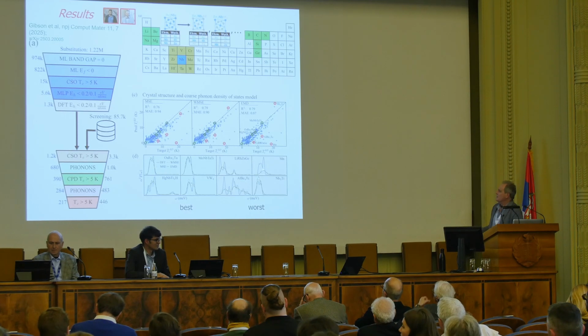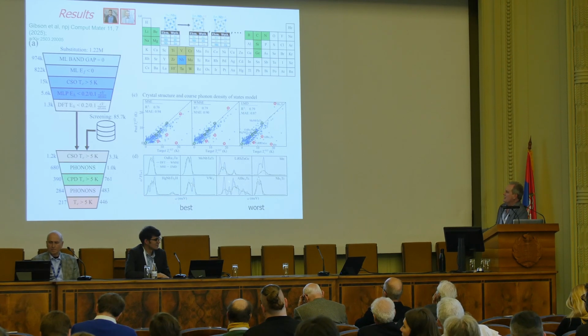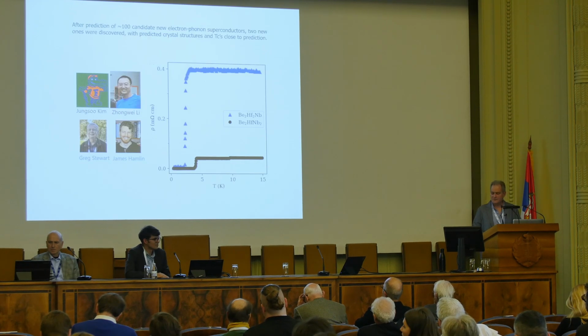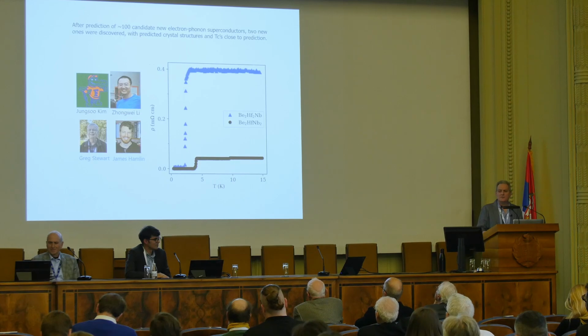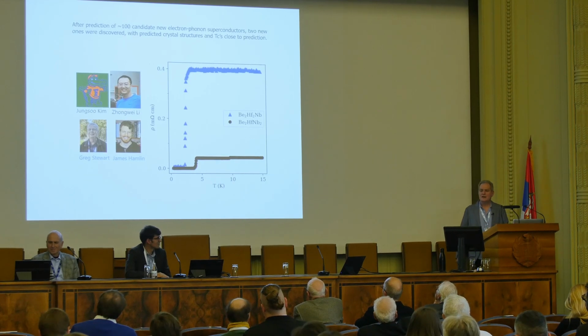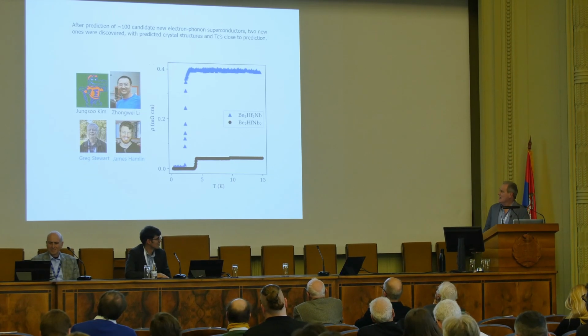The nice thing about the prediction of alpha squared F instead of TC is that you can go back and see which phonons you missed and try to do something different. So this is an indication that the theory is rather successful. At the end of this process, we came up with a list of 100 candidate superconductors, and we asked our friends in the laboratory to go out and synthesize some of them. And we found 2 new superconductors on this list.